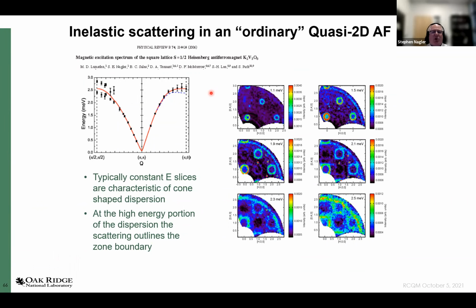So here we have a quasi 2D antiferromagnetic system, and I'm just putting up a plot here of a regular spin 1/2 antiferromagnet in 2 dimensions, just to give some idea what you sort of expect to see from, if you like, ordinary magnons. So if I was to measure these with a triple axis, I would measure an energy for various different values of Q, and I could plot a dispersion relation like this that shows the energy as a function of momentum. And if I think about rotating this about the vertical axis, I can see that, roughly speaking, I have sort of a conical dispersion.